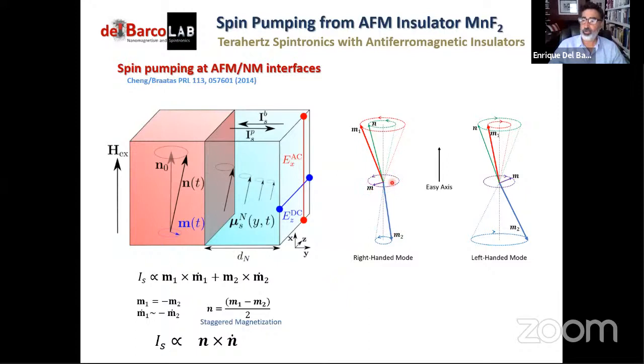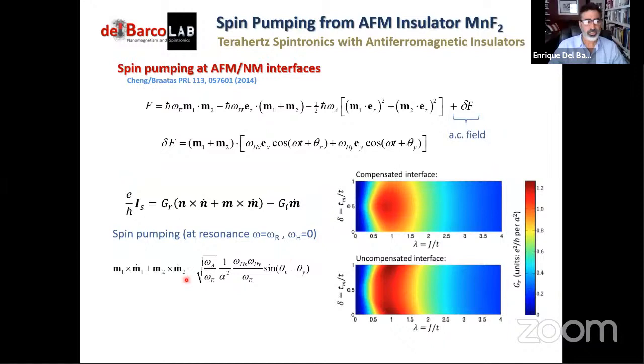a net magnetic moment oscillating in this plane, right? Because there will be a magnetic moment fixed going down because this projection is larger into the C axis than this, right? But also there's something that is going to change. So we cannot neglect that, although it's a much smaller term. So when you run the results at resonance, so you just hit the antiferromagnetic resonance, the spin pumping that is expected is going to be similar theoretically to what you would expect from a ferromagnetic material.